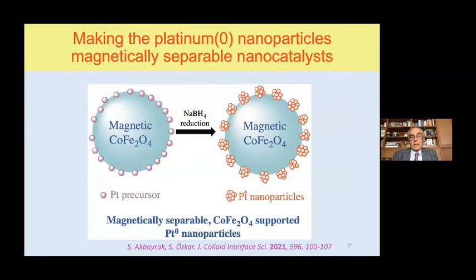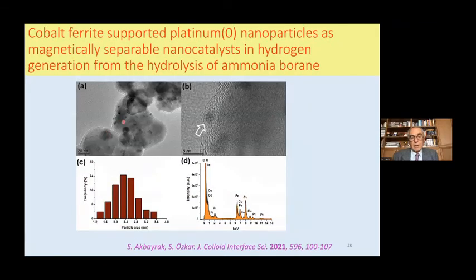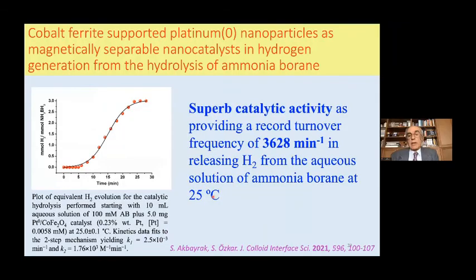So in the case of cobalt ferrite, platinum precursor can be impregnated on the surface of the magnetic core and reduced by sodium borohydride to form the nanoparticles on the surface of the magnetic core. So here we can see the nanoparticles on the surface of the magnetic cobalt ferrite, and the particle size distribution has been studied, and the EDX. So these nanoparticles show superb catalytic activity, 3,600 reciprocal minutes. That's huge, actually, at room temperature. That's a high or record activity at that time.